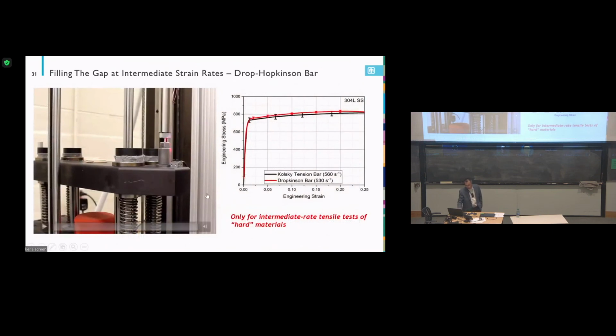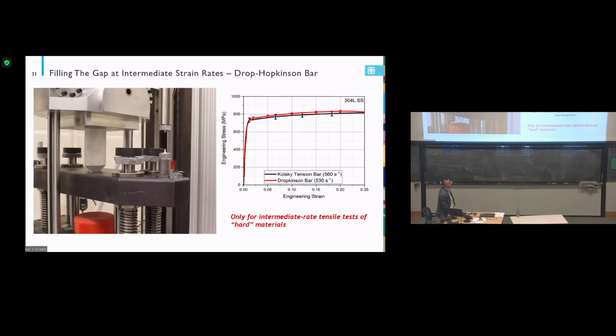So this is a video. This is not high-speed video, but regular video. You will see the big weight drop from the top here, hit on what we call a power striker that pulls the whole big plate down, then pulls the tensile specimen to fracture. So that's how we break this at an intermediate rate. And we can connect this to the Hopkinson bar test. We do some kind of verification test. It's pretty consistent.